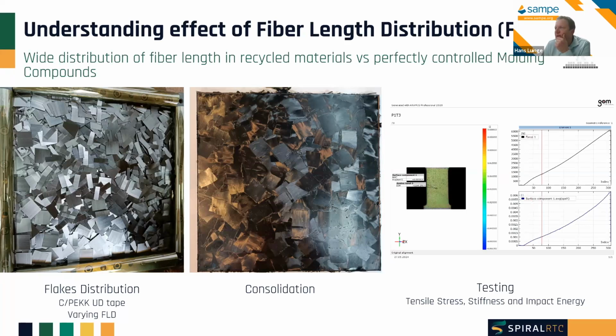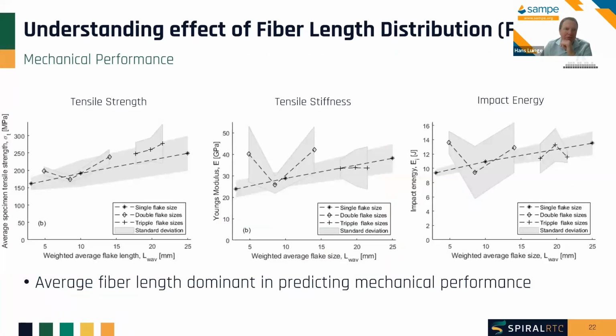One thing I would like to highlight is that this is looking at variations in the material and contaminations, but this is focusing on variations. So you have these molding compounds with typically a very controlled fiber length. So the question we ask ourselves is, if you do the recycling, you by definition have a broader distribution of fiber length, so what is the influence on the mechanical performance? We control that in a different way by mixing flakes of different lengths, mixing different fiber lengths together in different proportions, consolidating the material, and doing the testing. And that's typically tensile, stress, stiffness, and impact energy. So, what is the influence of fiber length and fiber distribution?